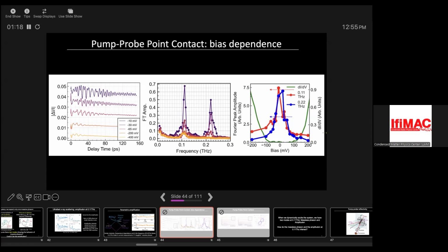Yeah, so the signal is localized, in the sense that because it's tunnel current and because the current is really coming from these exponentially decaying states, that signal is localized. We've done a lot of work on other things. For example, right now we're looking at a topological crystalline insulator, which has some edge states, and we can go to the edge and see a signal that's different from the bulk. So we have really good spatial resolution, and the tunnel current signal is pretty well localized. However, the actual physics is happening over very large scales. So even though the tunnel current information we're getting is local, the physics is happening over large length scales. Yeah, that is true, but that's true for many systems anyway.